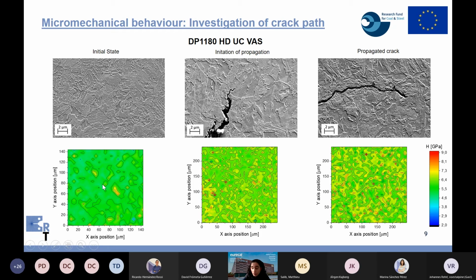Below the images, we can find the hardness distribution, and we can observe that both at crack initiation and when the crack is propagated, we can find in the hardness mappings some small harder islands that we think are related with the TRIP effect. It means these little harder islands are the transformation of the retained austenite to fresh martensite. We can observe that these little islands increase in stage 3, where the crack is propagated.